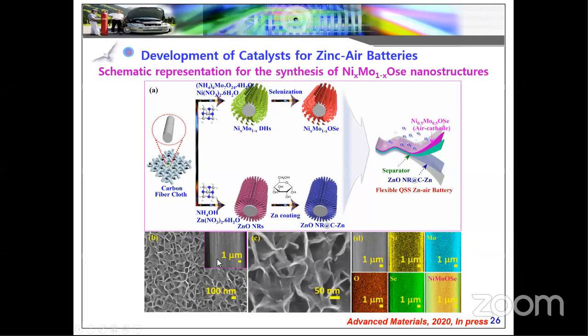On the carbon cloth, you can see ultrathin nanosheets uniformly grown. In the zoomed, high-resolution view, you can see each nanosheet interconnected with the others, and there is huge porosity. This porosity may be helpful for ion transport and increase the electrochemical activity, and the thickness of the sheet is very thin, so the active sites, especially the electroactive sites, are more numerous.